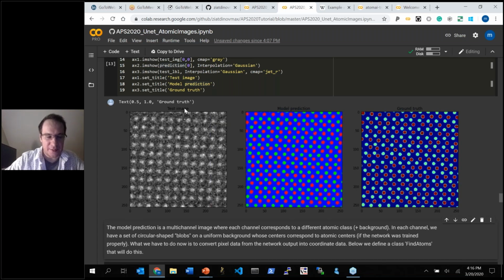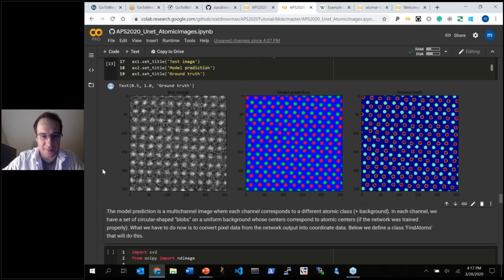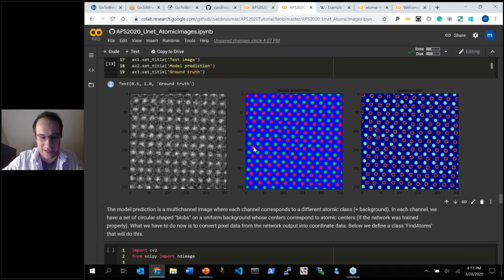And so here is the test image. It was not used for training, for weight optimization. You can see it on the left, and then here in the middle, you can see the model prediction. And this is the ground truth that the network has not seen. So you can see that our prediction is quite good. It was able to remove all the noise and then find all the atoms. And the most important part is that it is actually able to find the small local distortions. There are many other ways of cleaning images and finding atoms, but most of them are based on the FFT, and in that case, we won't be able to capture the small local distortions.